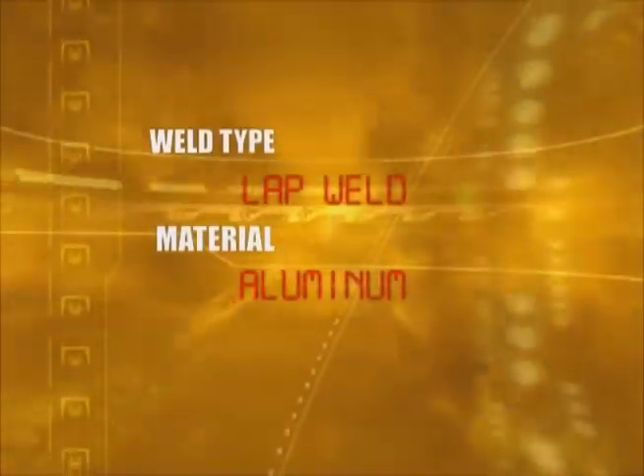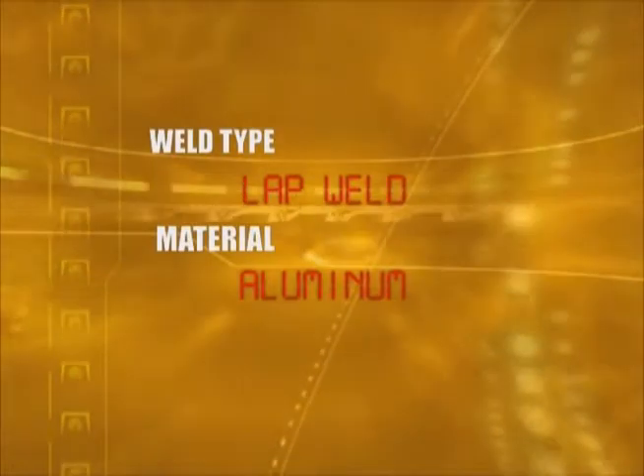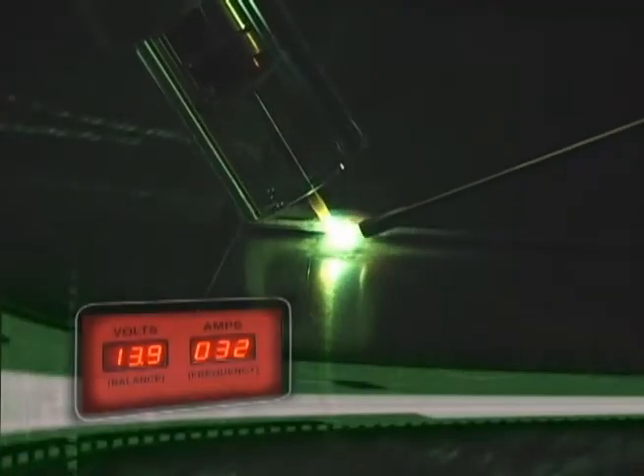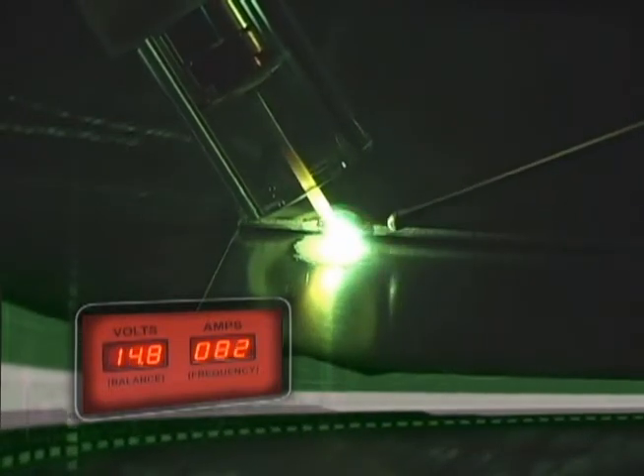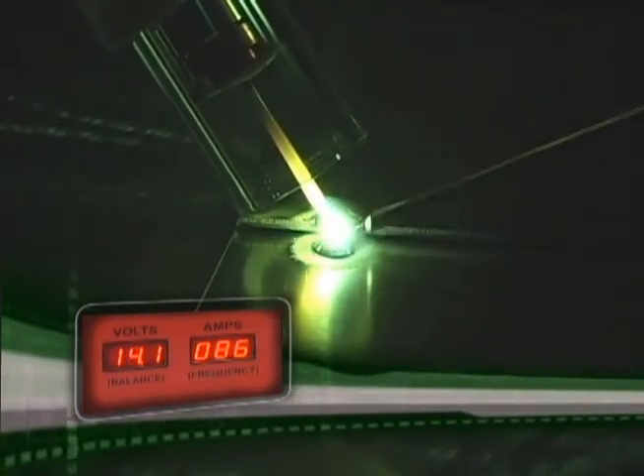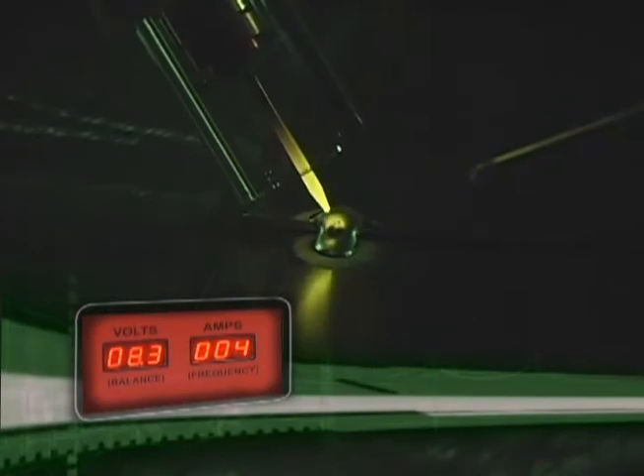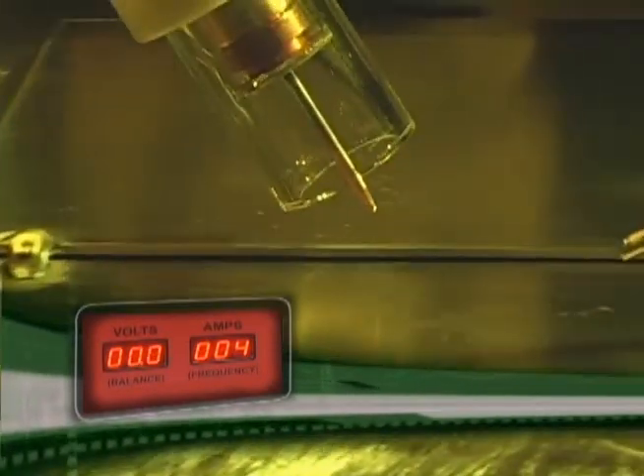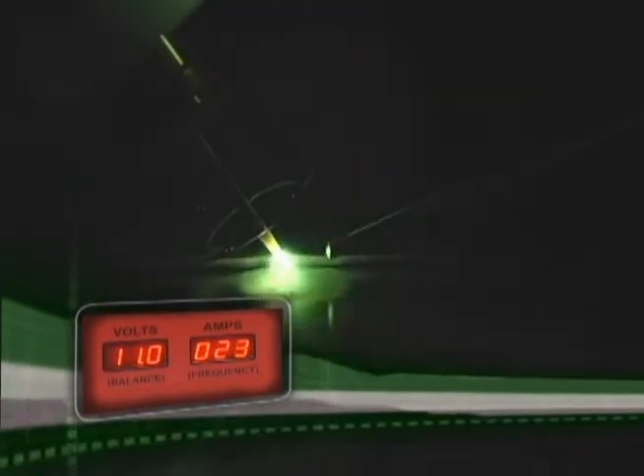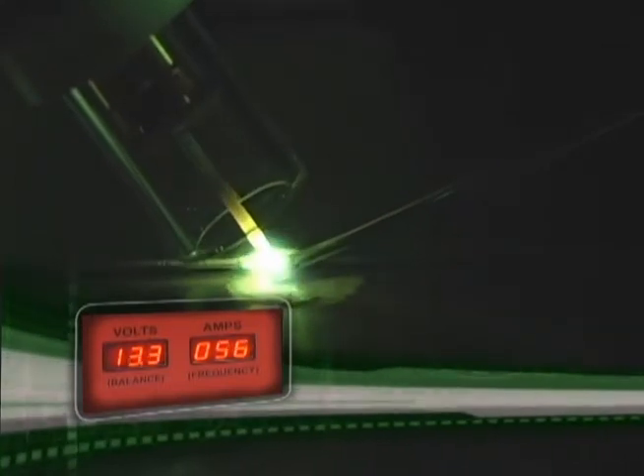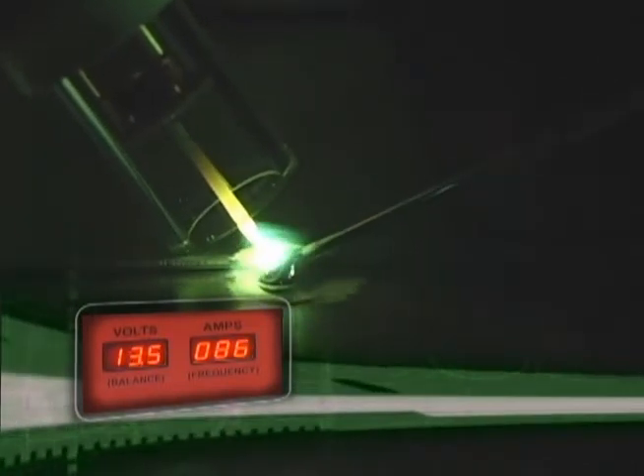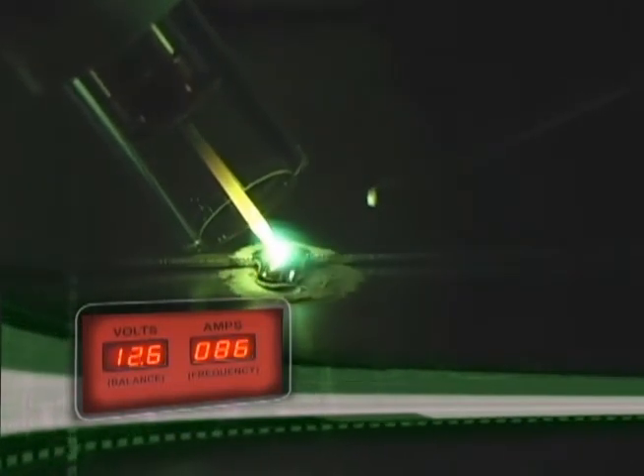Aluminum lap weld. This is trickier than a butt weld. You have to remember the arc will always be attracted to a sharp edge, so you want to initiate the arc on the lower panel away from the edge of the upper panel. As you increase the amperage, bring the torch closer to the upper panel, get a puddle going on the lower panel, dip the filler into the puddle, and again let it wick into the upper panel.